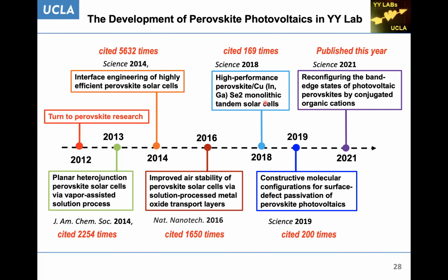In 2018, we published a paper using a perovskite and copper CIGS tandem device, and that is a world record efficiency for a tandem device with perovskite. In 2019, we published another paper in Science on a constructed molecule configuration for surface defect passivation of perovskite solar cells. This year, we published another paper in Science on reconfigurable band edge states, because we proved an organic molecule is able to modulate the band structure of the perovskite.